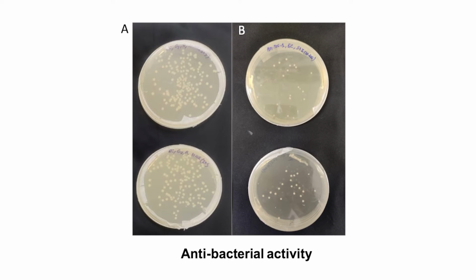Coming to the results of the anti-microbial, this is how the antibacterial activity looks. Here you can see that the number of colonies is really high on plain glass substrate. Here we have tested it against E. coli, but if you look at the coated substrate, you can see that the number of colonies has drastically reduced. So it shows a very high antibacterial activity of this surface coating.